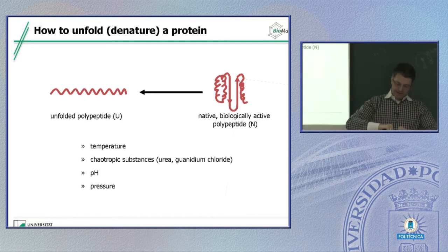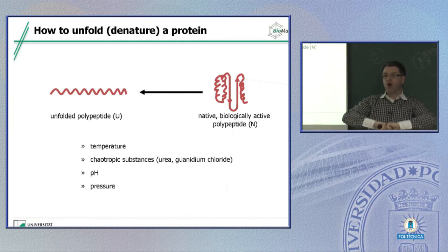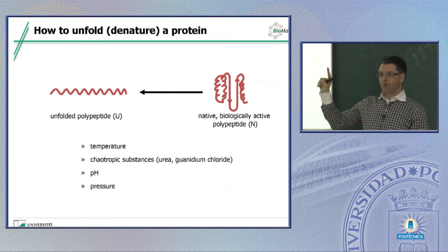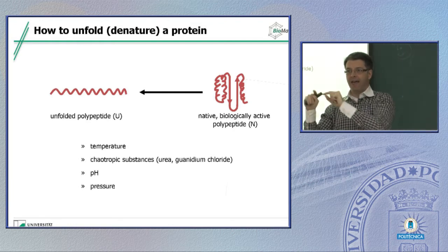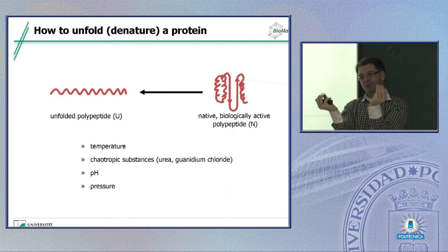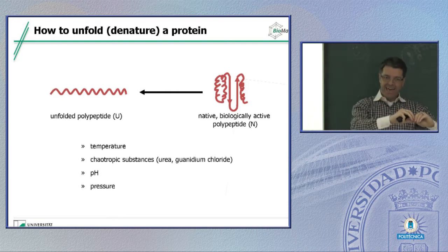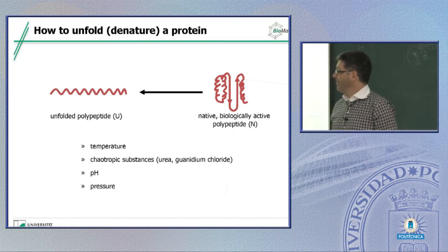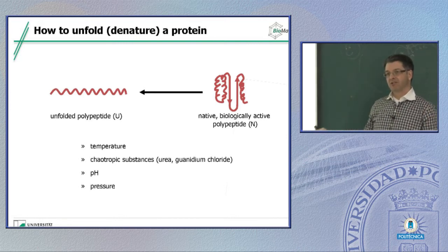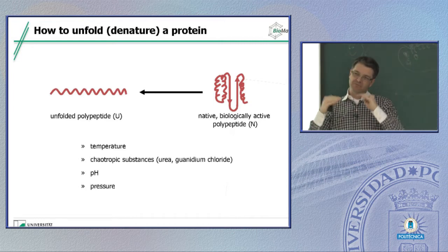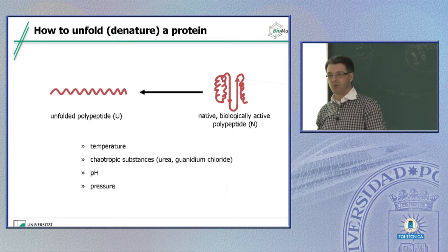And because the hydrophobic effect is gone at these low temperatures, it does not aggregate. So meaning, if you would, instead of boiling your egg, freeze your egg, you would have also an unfolding of the molecules, but you will not get the egg white because it will not aggregate. The problem is that for most cold denaturations, you have to go down, even below -20 degrees centigrade, and this is somewhat tricky in water.